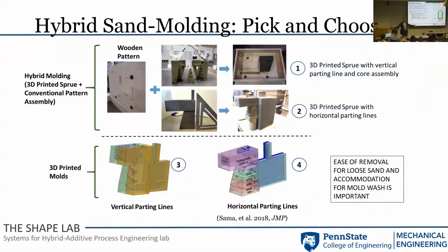And there are some examples that I cannot show, but I can roughly talk about it. This is a fairly simple geometry, right? There are some impeller parts that had much thinner cross sections where, with this conical helix, we had to be a little more creative and not have it all go in one direction, but have the conical helix actually go around the geometry. So the heat of the metal that's going to be left in the sprue would still make sure that you're going to fill the entire mold and it's going to solidify uniformly. So think of like a donut impeller, but then your sprue is actually traversing the entire cross section, and it's going to continue to cool down. So you're not going to feed from the middle; you're feeding from the outside.